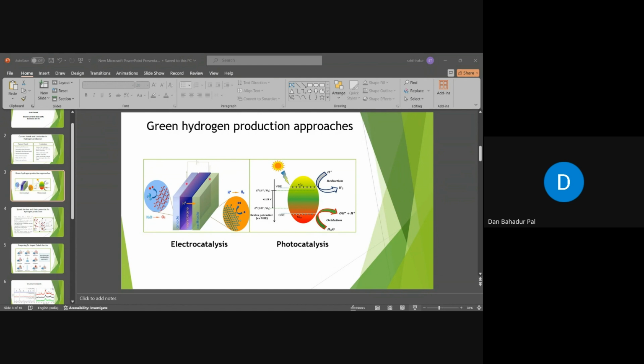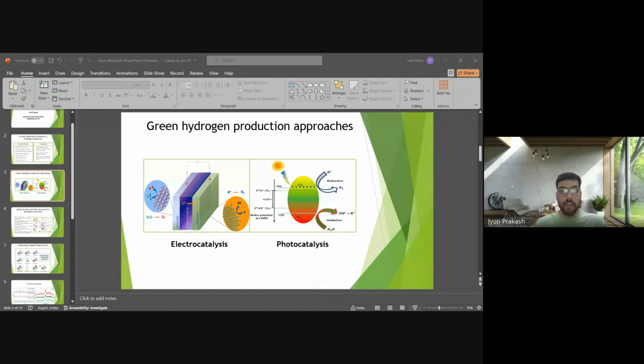Yes. Okay. So here in the diagram, we can see that spinel ferrites have two interstitial sites, octahedral and tetrahedral sites. The spinel ferrites show a moderate band gap, which is suitable for photocatalysis, and they are also chemically stable and show a higher mass to volume ratio for electrocatalysis. That's why we are going for the spinel ferrites. There are different kinds of spinel ferrite which could be produced, but we have used Zn substituted cobalt ferrite for both electrocatalysis and photocatalysis due to its appropriate band gap and stable chemical behavior.